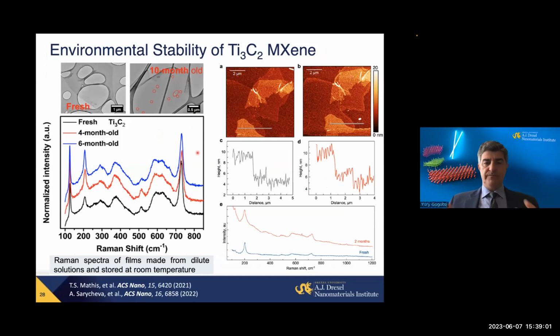A few things are important. Initially, MXenes were plagued by relatively low environmental stability, even though we always used to make them from aqueous solution, basically dispersion in water. But now we can make materials that can stay for 10 months in dilute solution. You see, for example, Raman spectra of titanium 3C2 MXene, and for several months there are no changes. Single flakes laying on a gold-coated silicon substrate, stored over 2 months in just a petri dish. You see no changes in atomic force microscopy images. Raman spectra show it's still MXene. The different background was a result of a different tip used for TERS analysis.